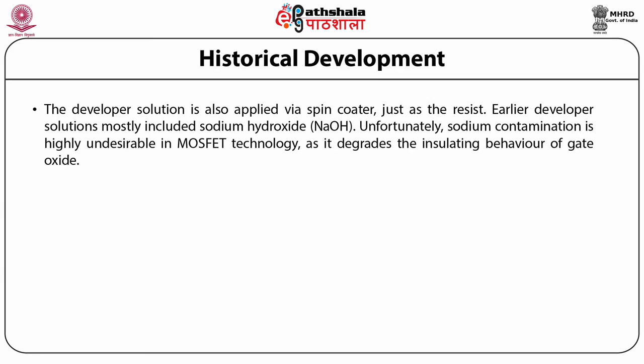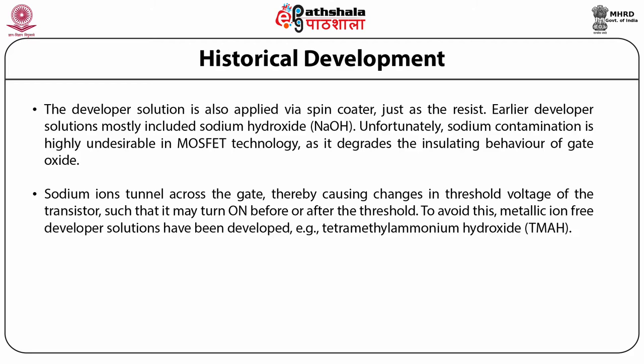The developer solution is also applied by a spin coater, just like resist. Earlier developer solutions mostly included sodium hydroxide. Unfortunately, sodium contamination is highly undesirable in MOSFET technology as it degrades the insulating behavior of the gate oxide. So, sodium ions tunnel across the gate, thereby causing changes in the threshold voltage of the transistor such that it may turn on before or after the threshold.